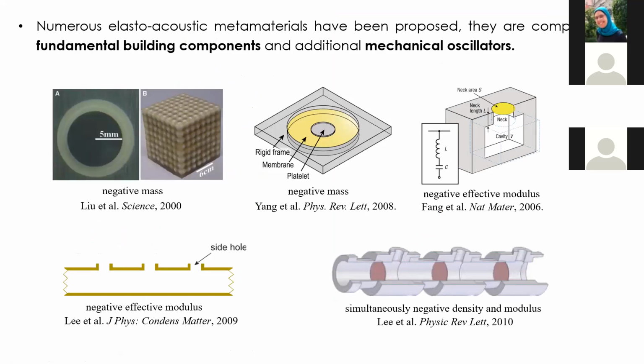Actually, numerous elastoacoustic materials have been proposed. They are composed of fundamental building components and additional mechanical oscillators. For example, the very first of these acoustic materials contains a hard core and soft coatings as the oscillator, and there are also some membranes as springs, and some attached platelets that work as mass. This is also an oscillator, and there are also the very famous Helmholtz resonators. An array of Helmholtz resonators can form a negative effective modulus acoustic material. There is also a tube with side holes, which can show negative effective modulus properties, and also tubes with both side holes and membranes.